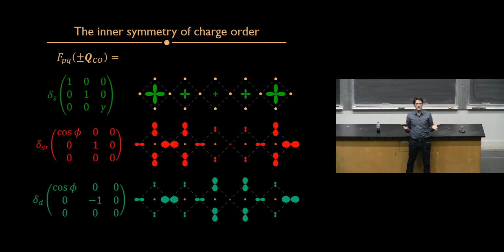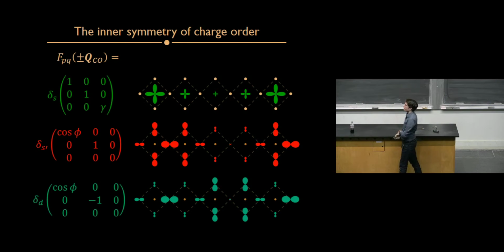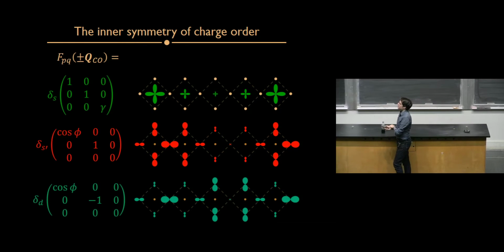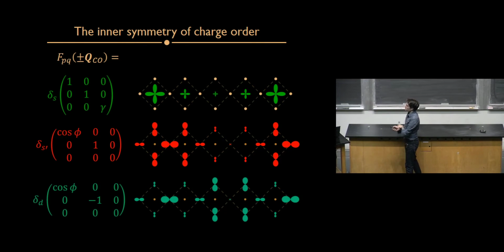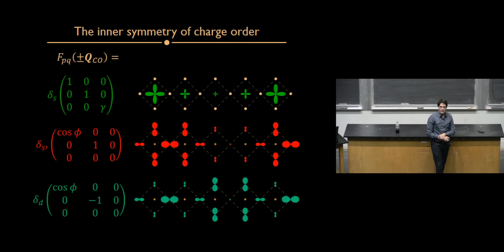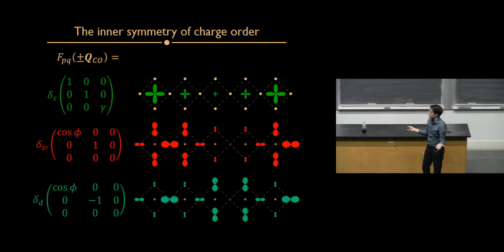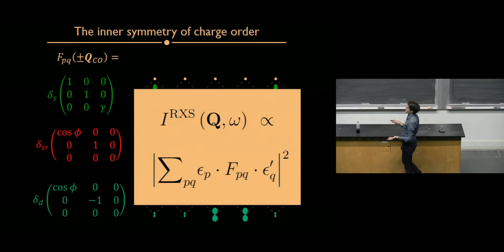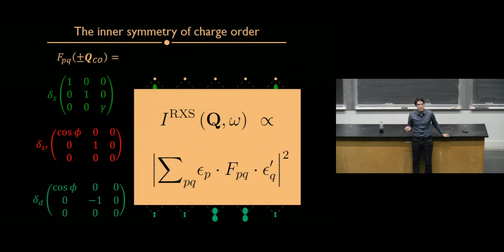scattering tensor. It's related to that tensorial quantity, the form factor that I introduced before. But it turns out we can map these three representations exactly onto three different representations of this scattering tensor. And this is where the beauty of resonant scattering comes in. We can measure this tensor by projecting it onto different polarization states of the incoming and outgoing X-ray photons.